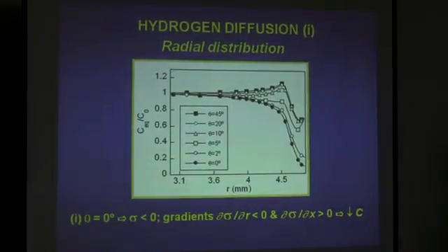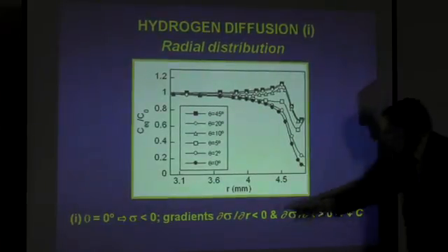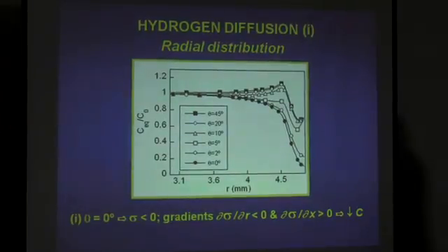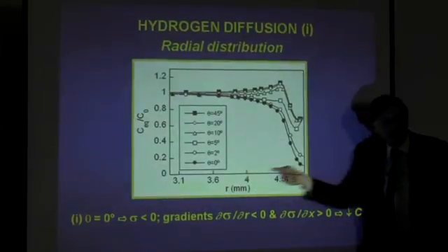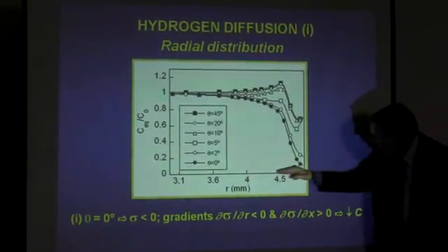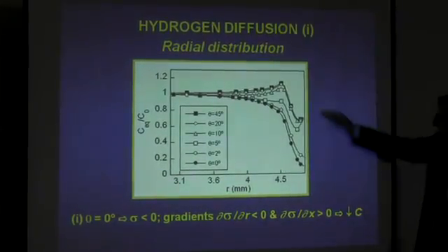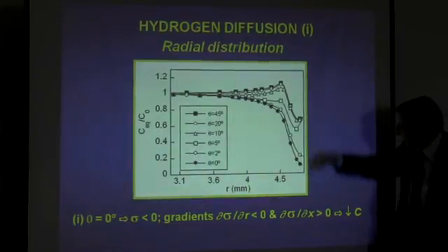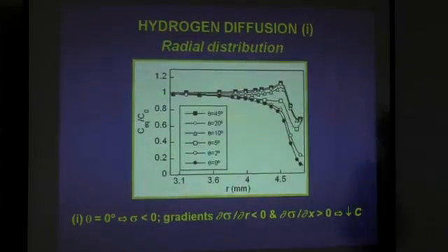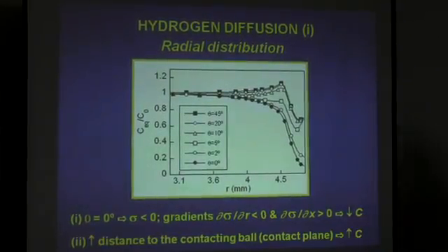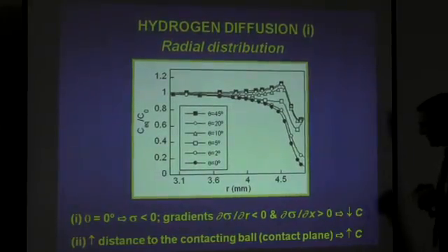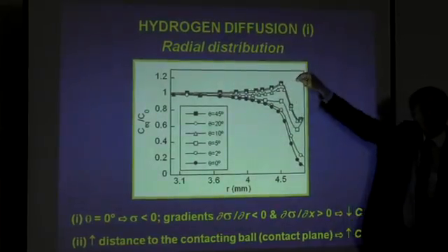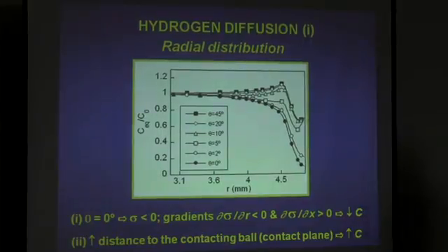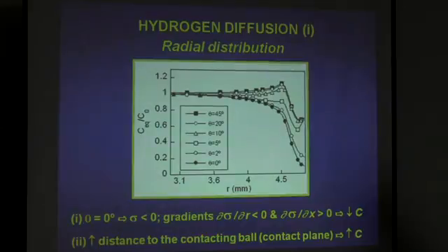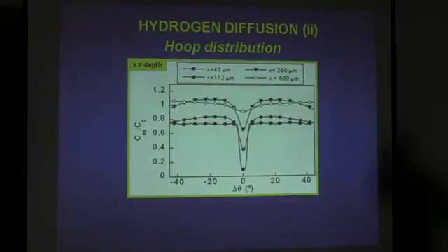And now some comments. At theta 0, negative hydrostatic stress, a negative radial gradient towards the right-hand side, but the inward gradient with the X variable, the penetration depth, not the radial coordinate, they are opposite. The inward gradient is positive, then lower concentration because of this boundary condition. The negative hydrostatic stress at the boundary predominates over the positive inward gradients. And as the distance to the contacting ball, to the contact plane, increases, the concentration increases. Maybe because the predominance of this strongly negative hydrostatic residual stress at the boundary vanishes as we are far away from the contact plane.